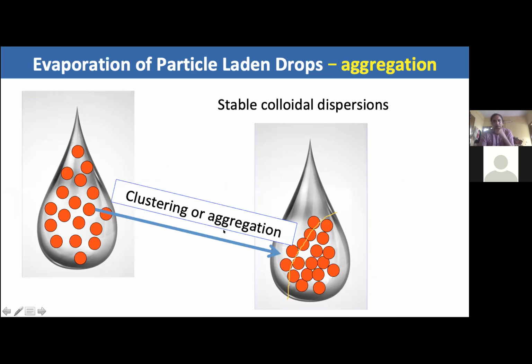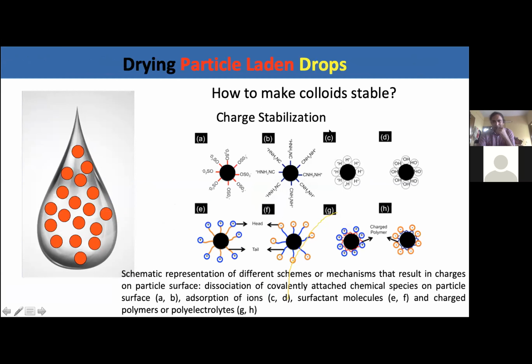Now, the other important consideration is that the particles during the course of evaporation or drying of drops should not cluster or aggregate. And therefore, it's again a good practice to work with stable colloidal dispersions, unless one is specifically interested to look at the effect of aggregation during drying. The dispersion can be made stable by using one of several stabilization mechanisms, the most common being what is shown in the schematics A and B, where there is a charge